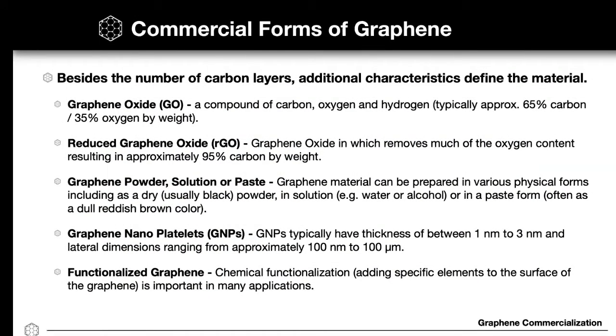You also have additional types and forms of graphene, including a graphene oxide material, which is produced with specific methodology, and it has approximately 35% oxygen by weight. This is an important material because it takes graphene, what is typically hydrophobic, and makes it hydrophilic because of the oxygen. It also takes graphene, which is highly electrically conductive, and makes it an insulative material. It's no longer conductive, again, because of the oxygen. You then have reduced graphene oxide, which is what it sounds like, a graphene oxide in which the oxygen has been reduced or removed. Graphene can be obtained, used, and sold as a powder, a solution, or a paste.